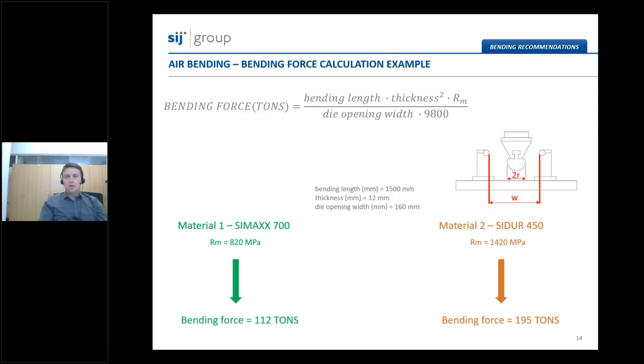So, in order to better present the required bending forces, we have two examples of the bending force calculation. The example is made on SIMAXX 700 grade compared to the very resistant grade SIDUR 450. Both plates have the same thickness, the same required bending length, and also the same tool opening. As you can see, the required force for SIMAXX 700 grade is approximately 110 tons. On the other side, we need almost 200 tons for SIDUR 450 grade. So the higher forces for SIDUR 450 are necessary due to the much higher mechanical properties compared to the SIMAXX 700 grade.